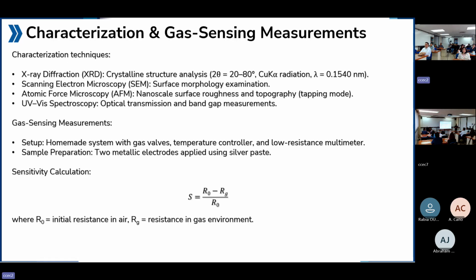Once all the coatings were in hand, we did the characterization techniques. The structural analysis was done with XRD, and to know the morphology of the films, we studied SEM analysis. AFM helped us to study the nanoscale topography of the film, and UV-Vis, on the other hand, helped us to know the optical transmittance and band gap changes.